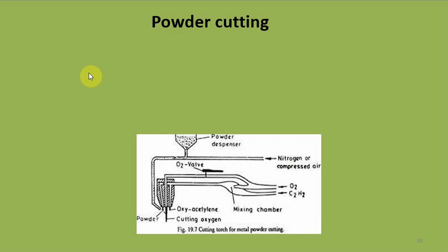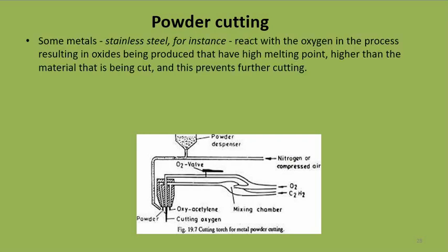The last method of cutting is powder cutting. Suppose we need to cut stainless steel. Stainless steel oxides have a property that they melt at a higher temperature than the stainless steel. But in the case of other steels, like cast iron or mild steel, the oxide will melt at a lower temperature than the base metal. That's the method we used in gas cutting. But here, since the stainless steel oxides melt at a higher temperature, we cannot use that same method. Why? Because if we want to use it, we have to elevate the temperature of the torch, and that is not effective.